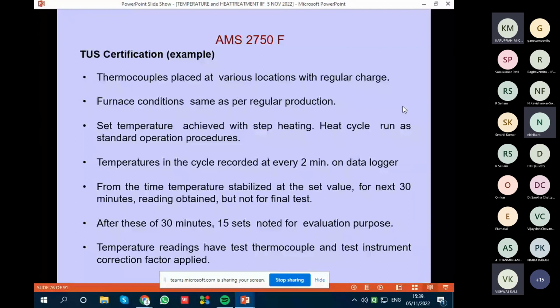For temperature uniformity, what we do, we put the thermocouples, as I showed you a little earlier, and we put a lot of thermocouples depending on the size of the furnace. Measure the data every 2 minutes and wait for the temperature to stabilize. When it stabilizes, then we take 15 sets for the evaluation, make corrections as per the calibration test certificates. That means I get the true readings of the thermocouple and the instrument.